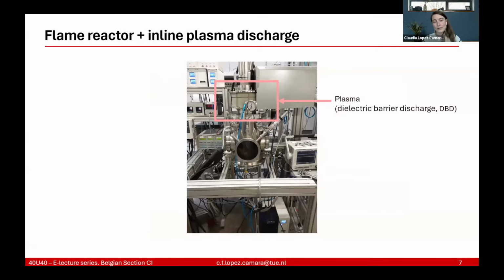So as well as you can do hybrids of plasma reactors with hot wall reactors, you can also do flame reactors, which is the same reactor that I showed you before with the matrix burner, but with plasma in line. And this is not a microwave plasma, but a dielectric barrier discharge plasma. That is because in this particular case, we tried to avoid the agglomeration of nanoparticles by charging them right after they were produced by the flame. So this is something where, as researchers, we also try to get creative to find ways to avoid this agglomeration and those undesirable results that we could be getting if we don't use one of these approaches.